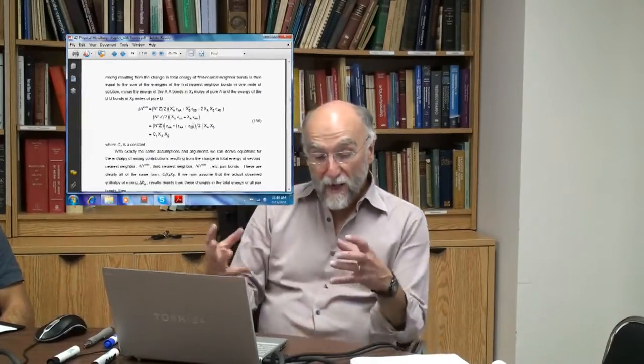So what happens then, if the AB bonds are stronger in the solution, this tends to stabilize the solution relative to pure materials, relative to an ideal solution, which gives you a negative contribution to delta H, which gives you a negative contribution to GXS, which makes the Gibbs energy more negative, and so the solution becomes more stable. So a stabilization because the bond energies are more stable. If epsilon AB is less negative than this, then the AB bonds are weaker than the average AA and BB bonds, and this entire term becomes positive. Gives you a positive C, a positive delta H, and therefore a positive contribution to GXS. So the AB bonds being weaker than the AA and BB bonds renders the solution less stable.